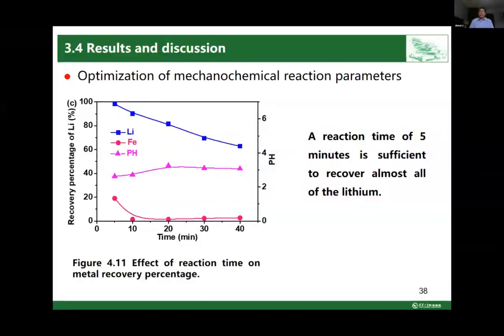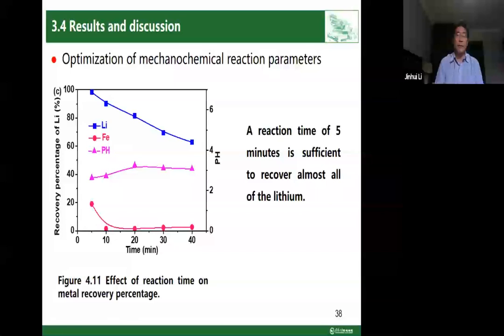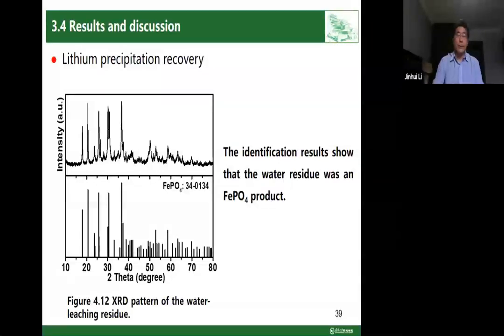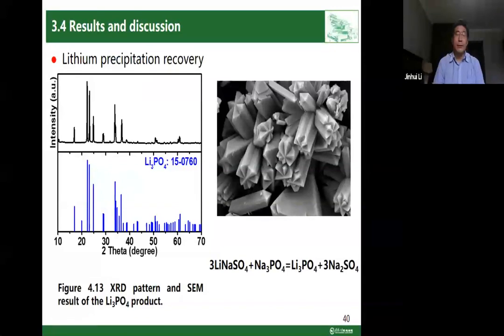So this figure shows the metal recovery efficiency with different ball milling times. The result of the study shows that 5 minutes is sufficient. So this is the XRD pattern of the water leaching residue. The identification results show that the water leaching residue is an iron phosphate product. So with sodium phosphate as a precipitant, lithium in the solution can be recovered by chemical precipitation to finally obtain lithium phosphate and sodium sulfate products.